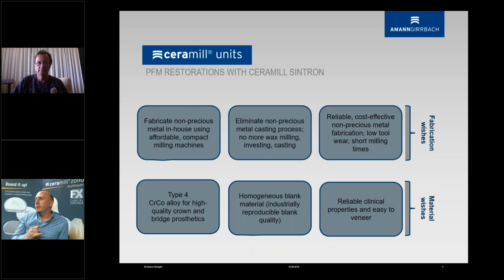But usually that's the sandblasting, as the black oxide eventually, which you can prevent by just skipping the oxidation altogether. And if you're consulting our manual from the Sintron, that's totally okay to do so. The one thing you don't want is to have it coming black out of the sinter furnace, right? Because that basically would tell you something went wrong with your argon gas. Maybe the bottle was empty, maybe there was a leak somewhere of some sort. So it never had the chance to create that atmosphere which prevents oxidation.